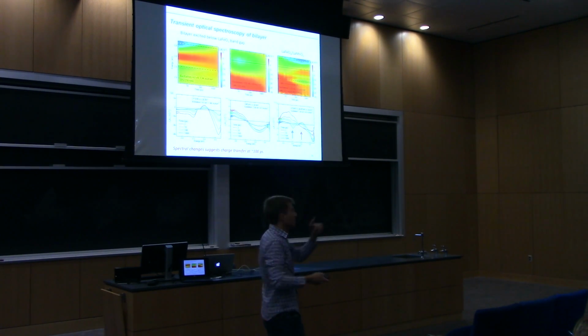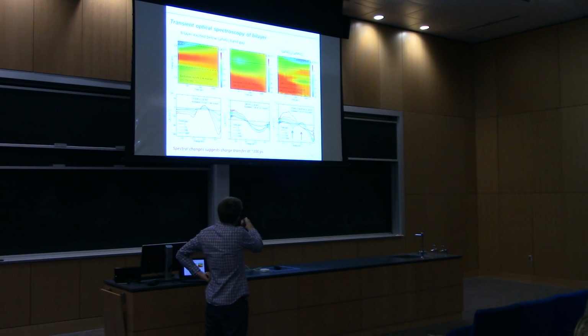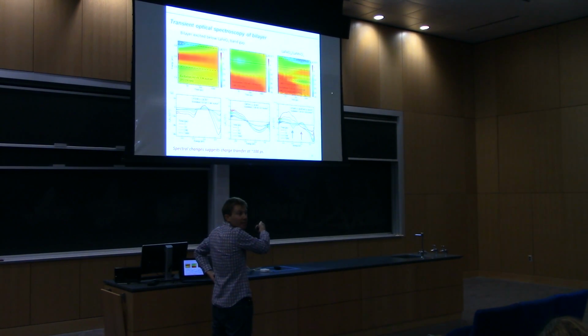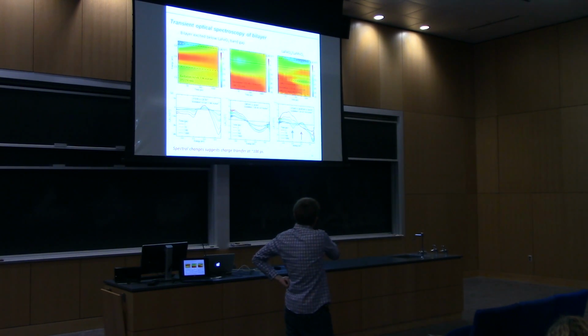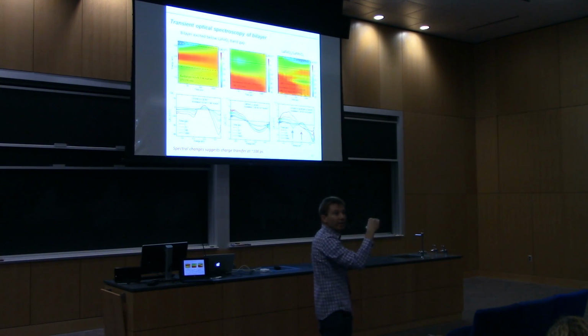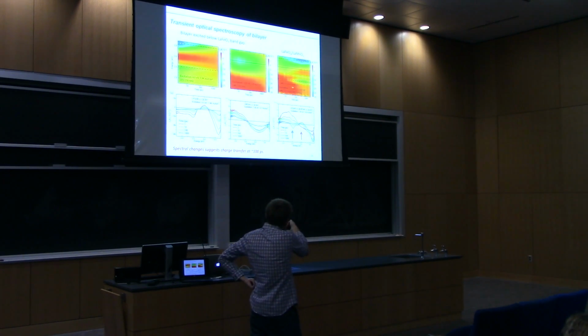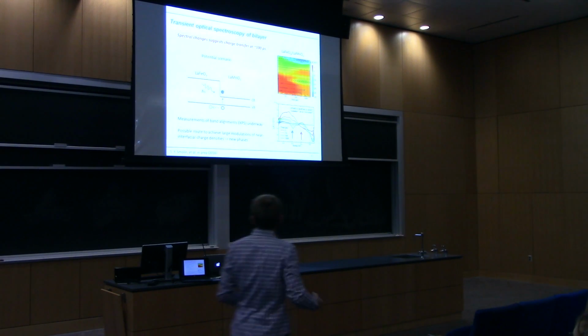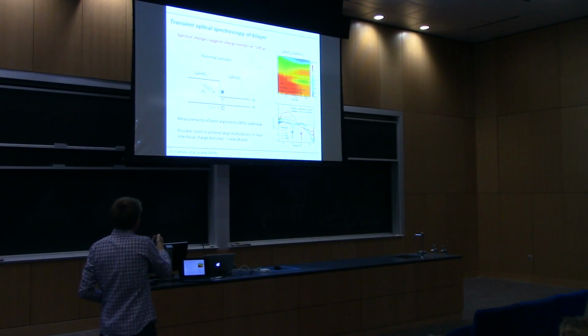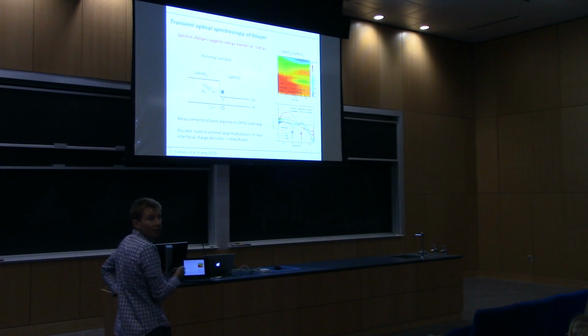The important thing that I forgot to mention is that this spectrum here is excited at 1.5 eV. This spectrum here is also excited at 1.5 eV. So this is excited below the band gap of LFO. In this data, we're not directly exciting any pairs within the LFO. We're exciting pairs within the LMO. And then over time, we're just probing the spectra, and the spectra start to look like LFO. To us, this suggests that maybe there's some charge transfer occurring on the order of 100 picoseconds.